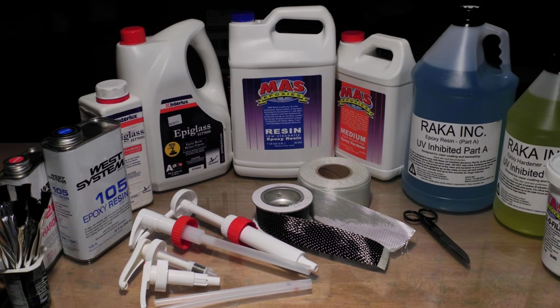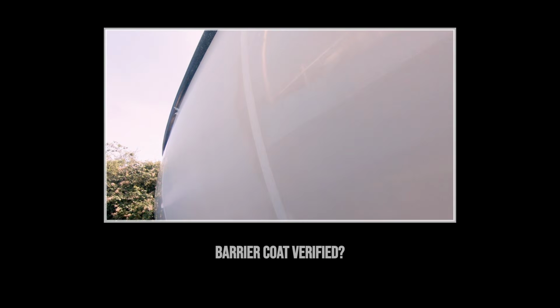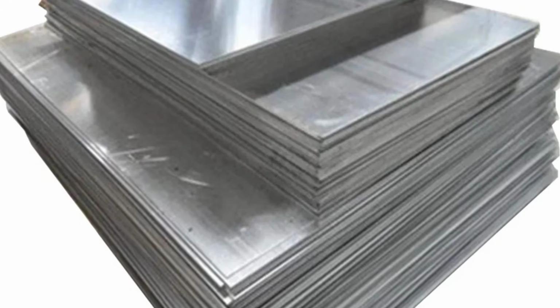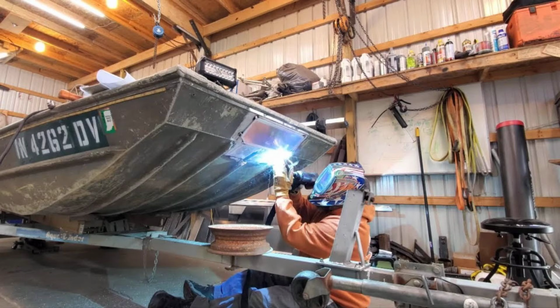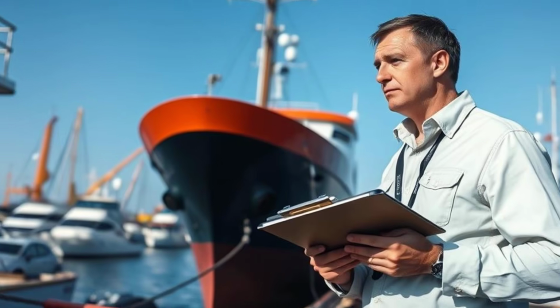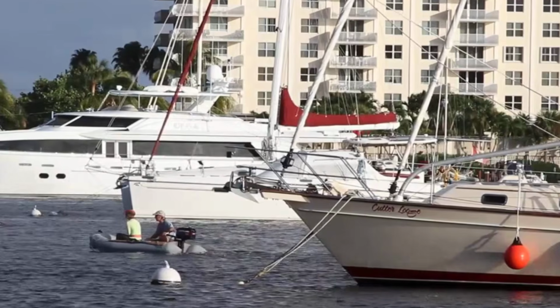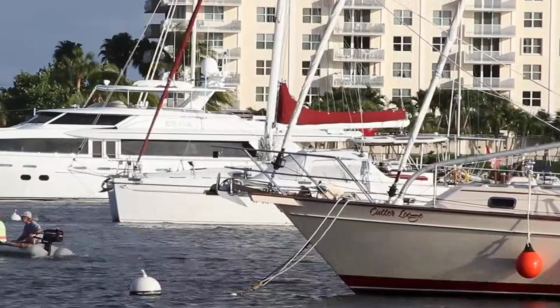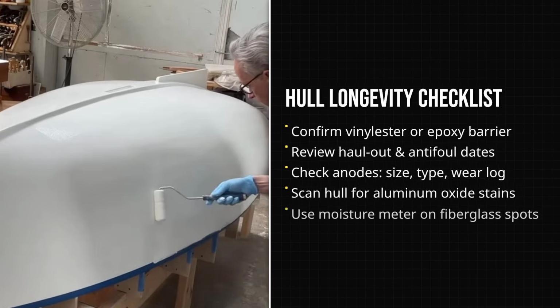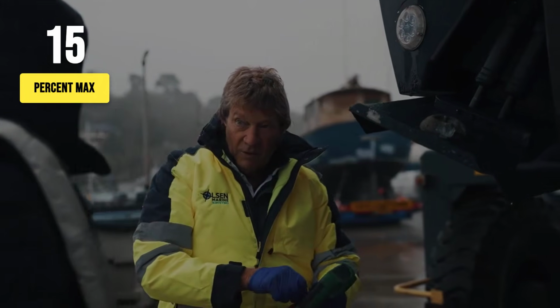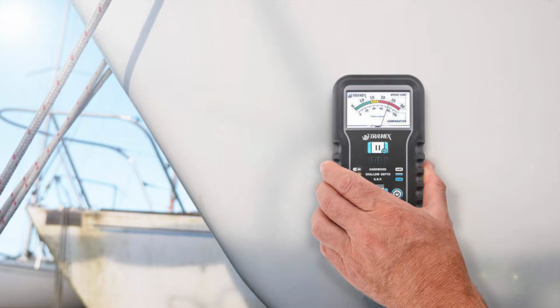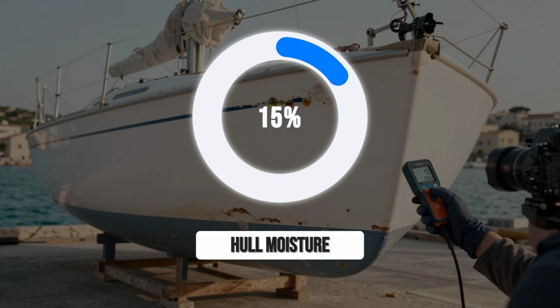The builder's choice of resin answers whether a fiberglass hull is protected against osmosis. The alloy specification answers whether an aluminum hull is built for marine service. Both of those questions need an answer before you evaluate a used boat. For fiberglass, confirm vinylester resin or a factory-applied epoxy barrier coat, check the service record for annual haul-outs, and run a moisture meter across the bottom. Above 12% moisture is elevated, above 15% means active intrusion.